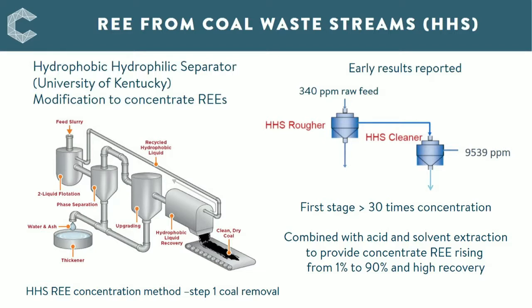Now, this is the first step, but the second part, which I'm not discussing today but is in the report, is probably more important, as this has to concentrate the rare earths from 1 to 90%. And that plant requires multiple stages of acid and solvent extraction and also thermal treatment under acid. The ability to concentrate at these levels in a relatively straightforward way is a major step forward and uses similar technology to that found in an ore smelter. As these processes avoid ore mining costs and everything involved in the mine and are simply an add-on to a beneficiation plant, there's a substantial margin to allow for a more dilute coal feedstock.